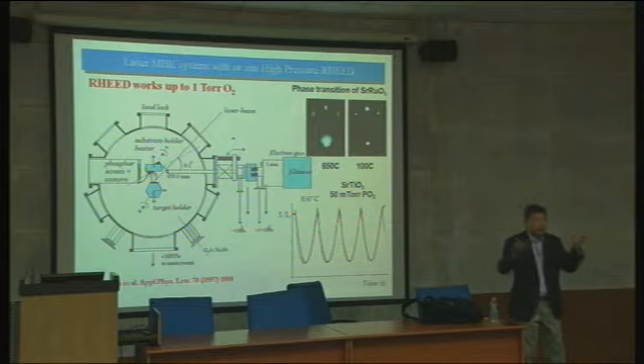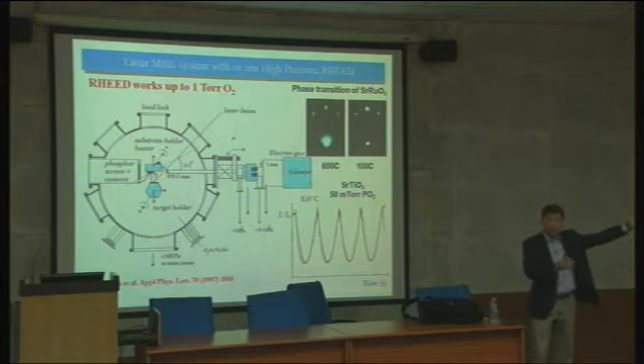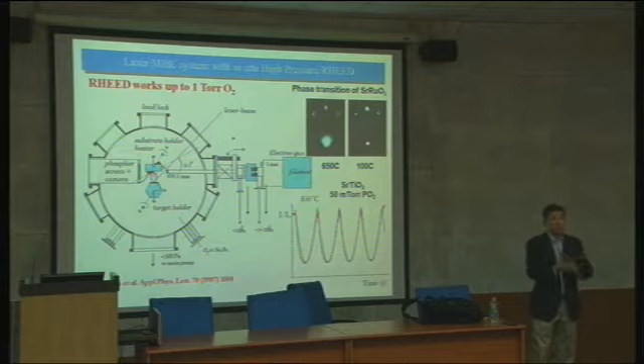So your mean free path is very short. That means normal RHEED guns, which work in semiconductors over very far distances, like from the electron beam to the sample to the imaging plate, a very long distance, where you can do the image. But if you have this long distance here, it is all scattered and you don't see anything. So you have to make this distance very short, not a meter, but 5 or 10 centimeters, about a factor of 10 smaller, to make this image possible.